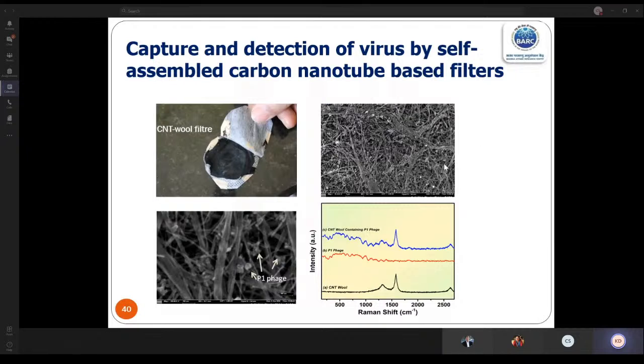Recently, during COVID time, we started to see whether there is a possibility to use a filter based on carbon nanotube to capture the virus and also to detect them. As you can see, carbon nanotubes can have porosity in the range below 100 nanometer. And these viruses, typically this COVID virus, are in the size of 80 to 120 nanometer. So we have carried out some experiments with phages. A phage is a virus of bacteria. So it will not harm a human, but it is a virus to the bacteria. So we can handle them in our laboratory because we cannot handle the COVID virus here.